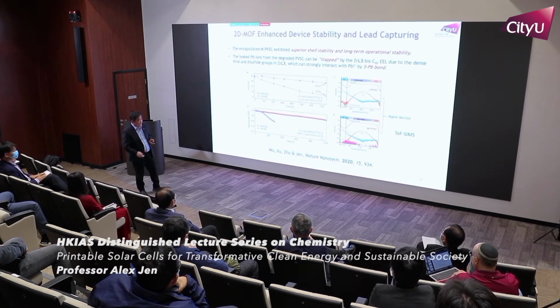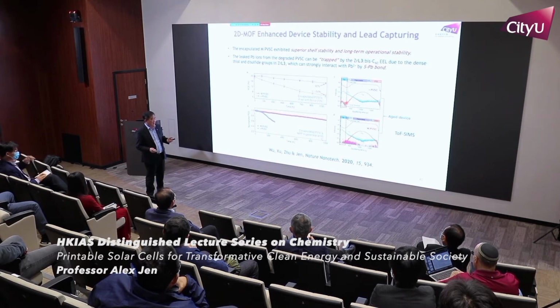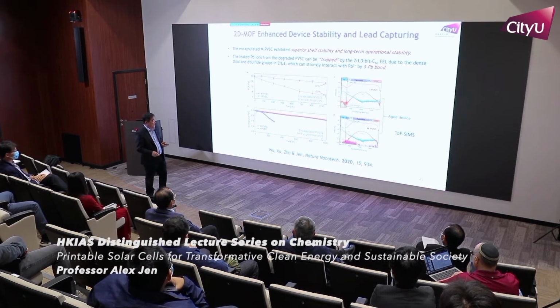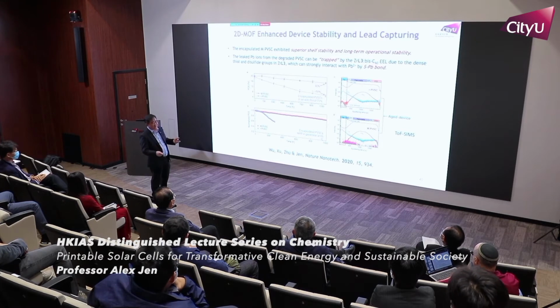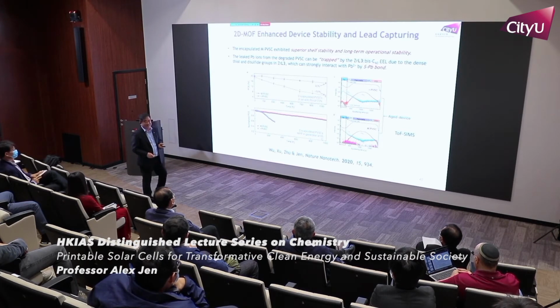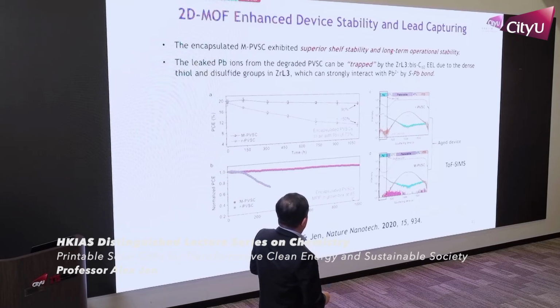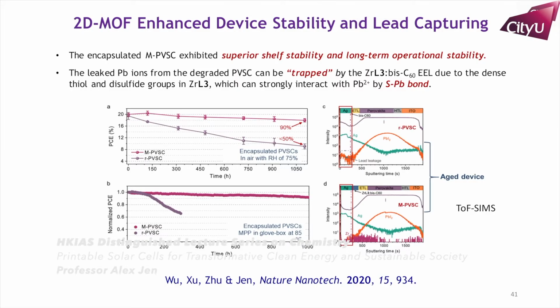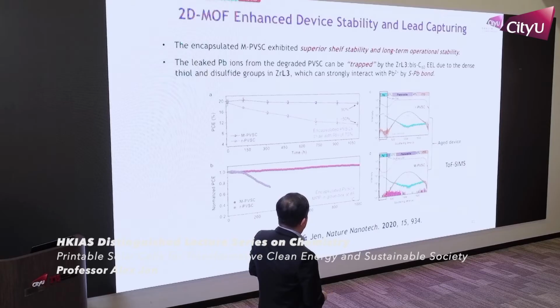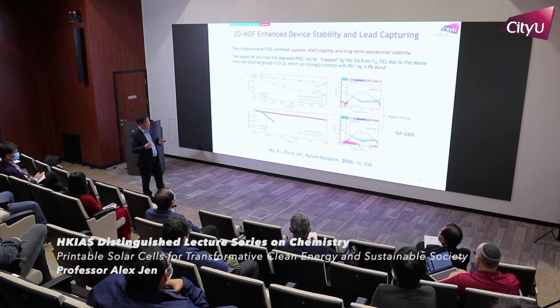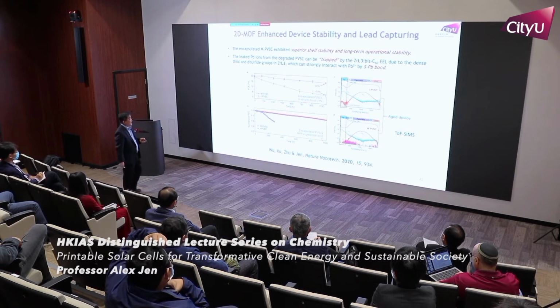And if you're asking why we can indeed capture lead, we use TOF-SIMS, time of flight secondary ion mass spectrometry. You can see that without this MOF, when you expose to those humid conditions, the perovskite decomposes, and the lead starts to diffuse out and go all the way to the silver electrode. But once you have that MOF covered layer, the MOF basically absorbs all the lead and prevents it from penetrating to the electrode.